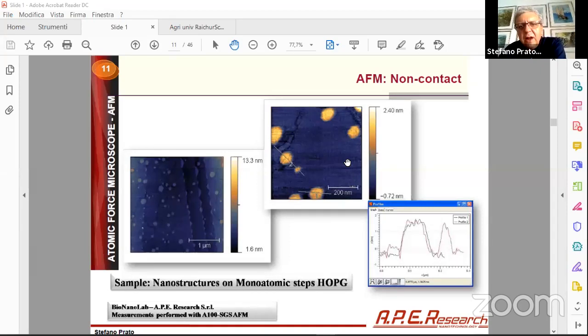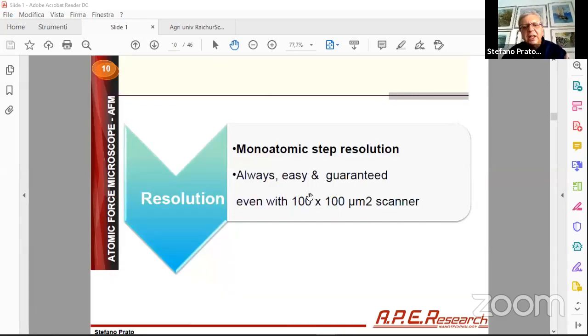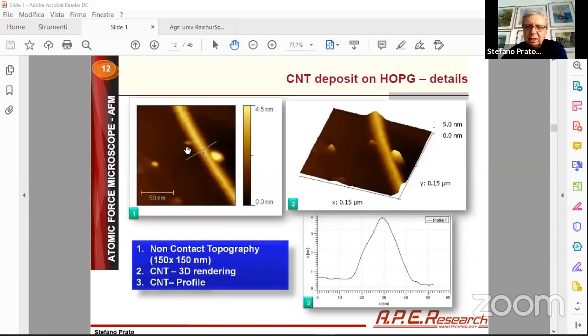It's one of the few methods that will allow you to watch in the nanoscale without really touching your sample. With X-ray you will bombard with X-rays, and with the scanning electron microscope we bombard with electrons. In this case, we do not touch the surface, so we have a picture of a very pristine sample. So this was about the resolution. This is a peculiarity of our AFM, that you can perform images that go from 100 micron by 100 micron down to very small, let's say a few nanometers by a few nanometers scan size.